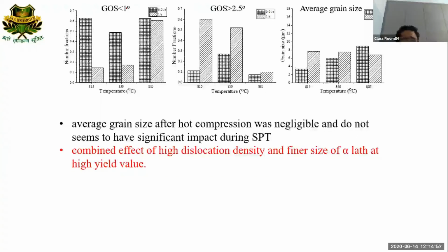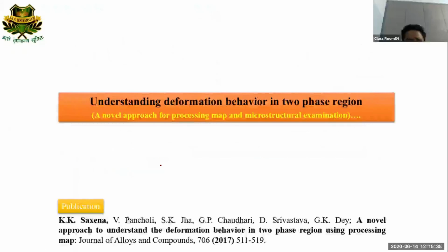or you can say that the microstructure or the grains faced only the deformation, not any kind of recrystallization or recovery. And in the right side figure, you can see the average grain size. Okay, for specific conditions we have plotted the average grain size data. And finally, we found that the combined effect of high dislocation density and the fine size of the alpha plates at high yield is the cause of the high yield value at that particular condition, which was 815 degree and 1 strain rate. Okay, so I'm stopping my talk over here and we'll open the session for question and answer.